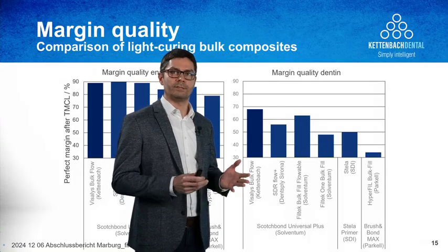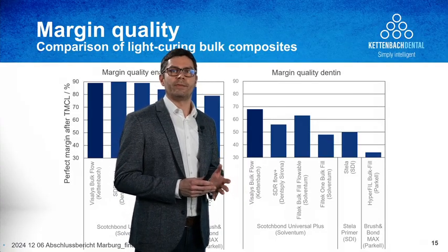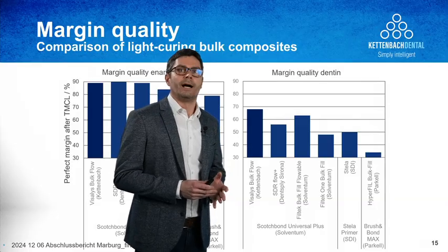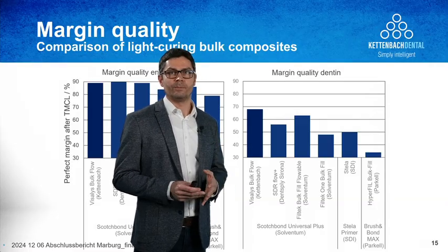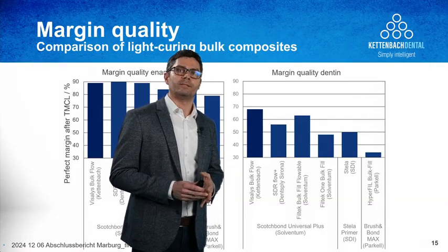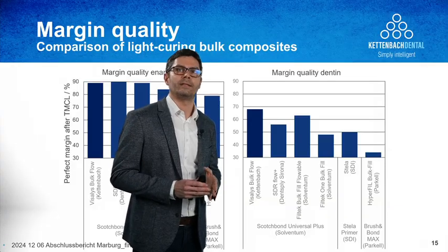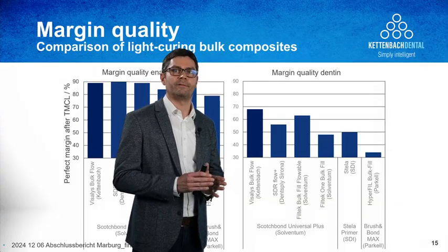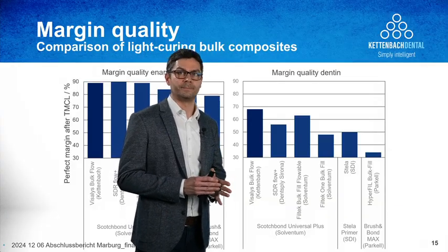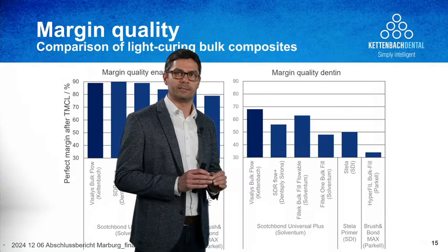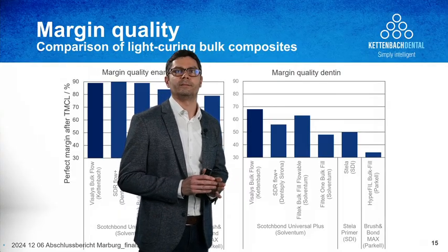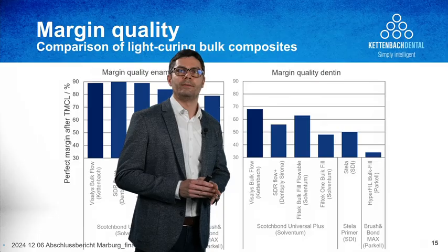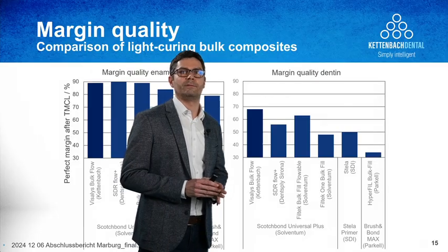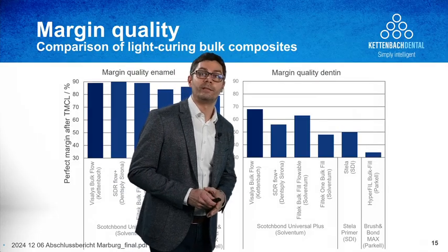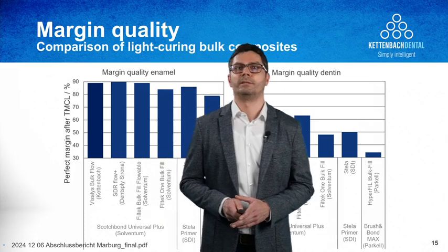So what's the process behind the dentin? In theory, or even in practice, after these chewing cycles and the thermocycling, you do get the degradation of the dentin. So it's very hard to get very nice results at this interface of composite and dentin. Something around 70% is the best that you can get. And you can see that Visalys Bulk Flow, in this case, has something around 70% and is therefore very good even on the margin quality itself.